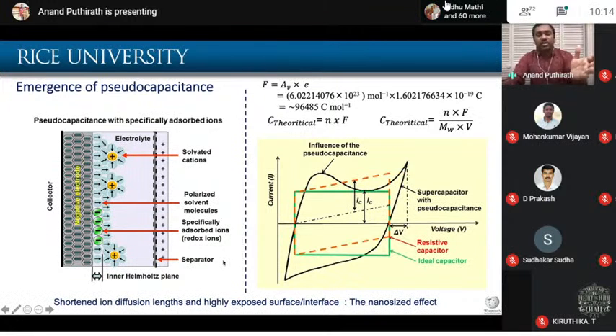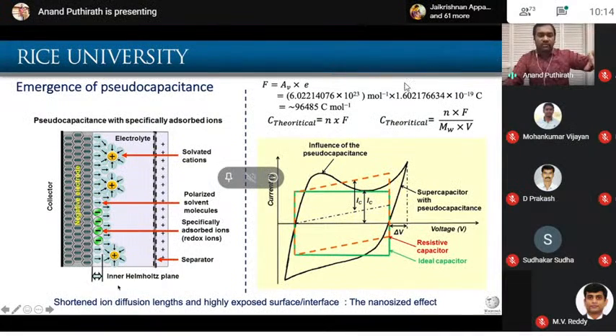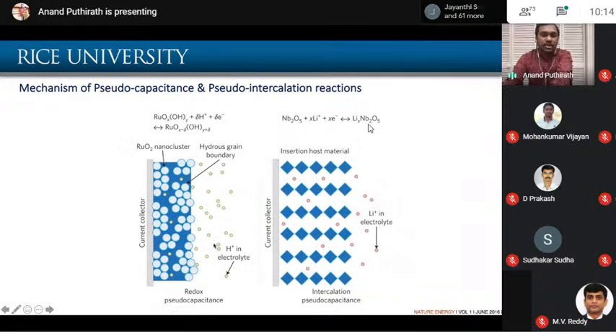And if you have a nanomaterial, the good part is that all the charges can come to the surface and they can be stored very easily. And the diffusion length and the exposed surface interface area are very favorable for nanomaterials. Basically, the nano size effect. And if you look at pseudo capacitance, it's not a full reaction.